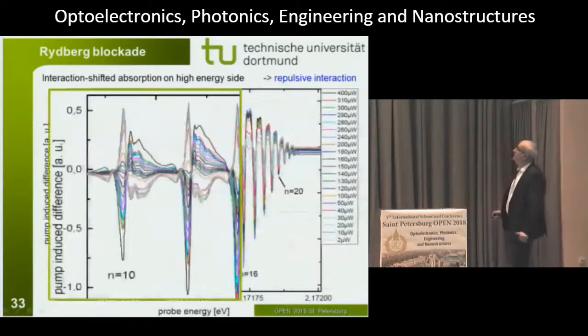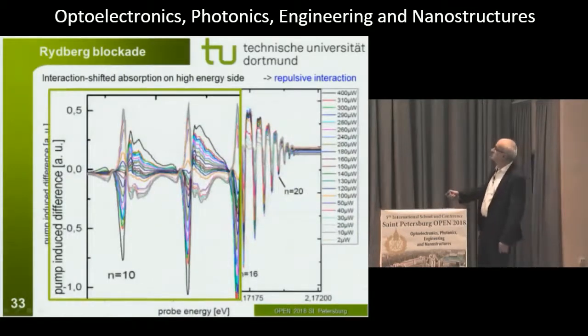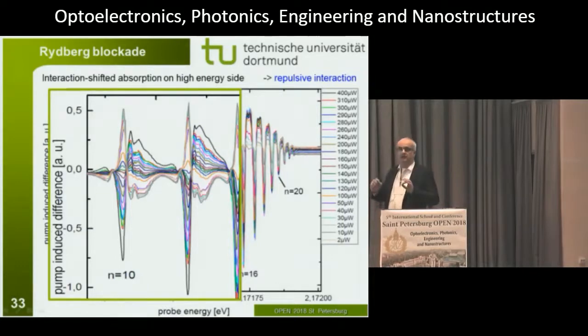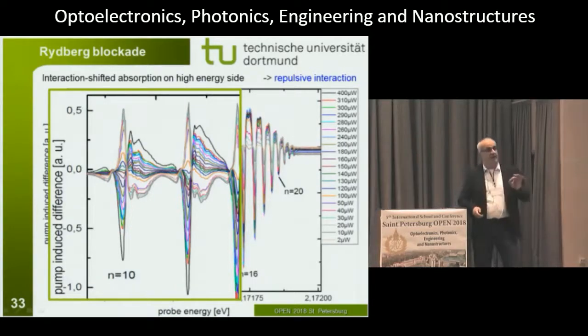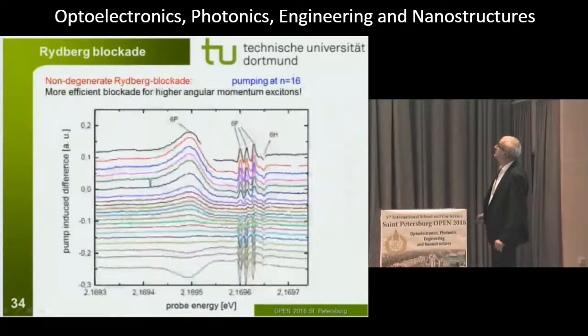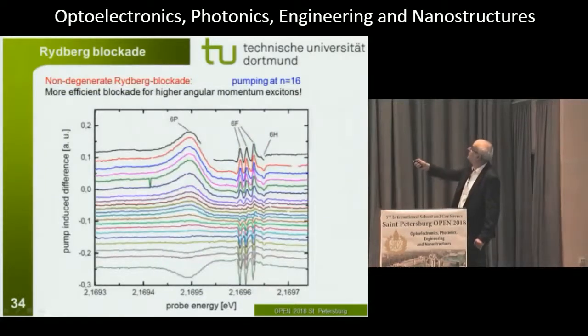There are a lot of other interesting features here. For example, if you zoom in here in the n equals 10 case, you see that the main absorption line becomes blocked when you increase the excitation power. But simultaneously on the high energy side, increased absorption shows up. And from this we uniquely conclude that our interaction between excitons is repulsive. It's not an attractive interaction, but a repulsive interaction, and there are many more things that need to be studied. For example, if you look at different angular momentum of the excitons, these are the p excitons, these are the f excitons.